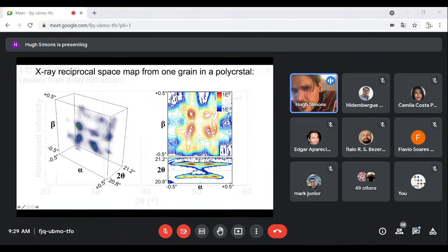Now, there's an expectation in ferroelectrics that because they're very strongly twinned, the peaks in the diffraction in the reciprocal space should be very nicely separated. So they should be in this kind of square pattern, which is what we see here. And in general, this is exactly what we see. But the problem is that you also have all this other sort of diffuse intensity in between. And so this diffuse intensity comes from things like strain, it comes from unusual twinning angles, it comes from dislocations.